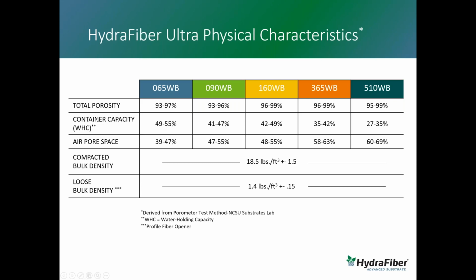When we look at container capacity, again, this is the portion of water-filled pores of the total porosity. We see that about 50% of the total porosity for 065, for example, is going to be water-filled pores. Whereas when we look at HF510 WB, roughly 30% of the total porosity is going to be water-filled pores. So 510 is going to have much less water holding capacity than 065 will. And then if we look at the air-filled porosity, about 40% or 45% of the total porosity is going to have air. And when we look at the coarser fibers, we see a lot more airspace in those fibers.